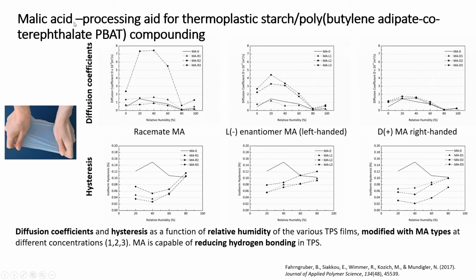Another one was malic acid addition as a processing aid to the same material. It's a slightly different type of thermoplastic starch because we had this PBAT copolymer included. And here you're seeing the diffusion coefficient that we calculated, so the rate of moisture vapor transfer through the film using the pan cell. You see all kinds of results here. I won't go into all the details, but what you see are basically three blocks of graphs, because we used different types of malic acid additive: the mixture, the racemate, the left-handed enantiomer malic acid, and the right-handed